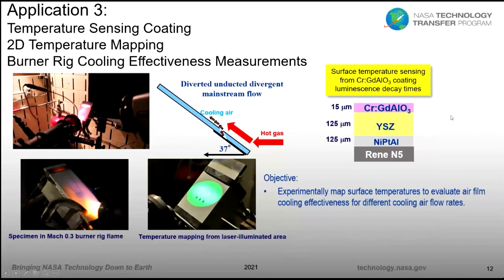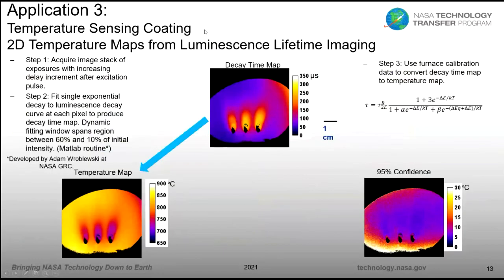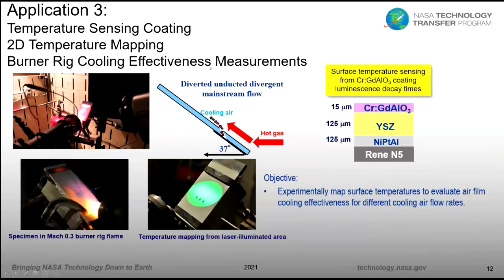Now, let me go on to the last implementation, also using a temperature sensing coating. Oops. Let's go back there. Sorry about that. I think this is even more impressive, getting a whole 2D temperature sensitive map. In this case, we're using the mapping to look at cooling effectiveness as we change cooling airflows through holes. Well, the plan is for components, but we're starting for simplicity with test plates because the analysis of the cooling is much simpler than for holes in the actual turbine component.